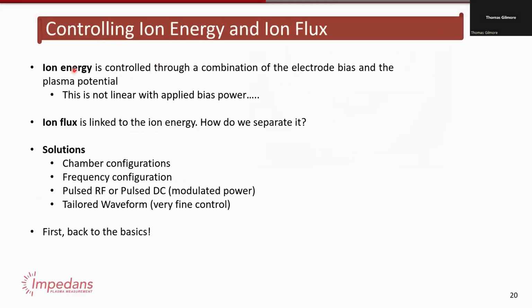So just going back to this topic. Ion energy is controlled through a combination of effectively the electrode bias and the plasma potential. They're the two key drivers. The electrode bias is not linear with bias power. Similarly, the ion flux is linked to the ion energy. So as you apply different powers, you could be changing the plasma potential or changing the electrode bias. But you're also changing the density. When you're changing the density, you can also be changing these two parameters. So this is typically linked. So we have to talk about how do we separate these? How can we have independent control over these two things? And there's a number of different solutions to that.